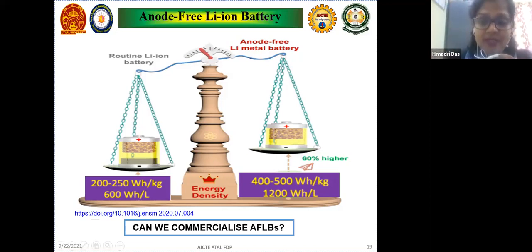And as I mentioned, the energy density we have reached for the lithium ion battery is not sufficient. Here we can see that with an anode free battery, the energy density can be more than around 1200 watt hours per liter. So it's almost 60% higher than the current existing lithium ion battery.